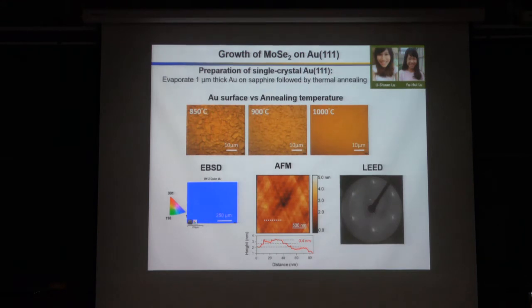And also we use low energy electron diffraction. You can see very clear hexagonal spots. The beam size is millimeter scale, so actually the natural orientation is the same. The crystal has the same crystal orientation. So after preparing the single crystal gold surface, I have to say, if you deposit wafer scale gold up to 1 micron,